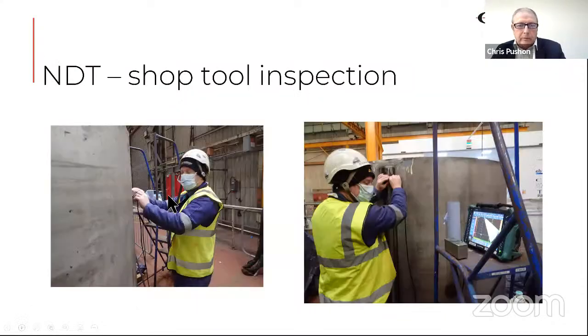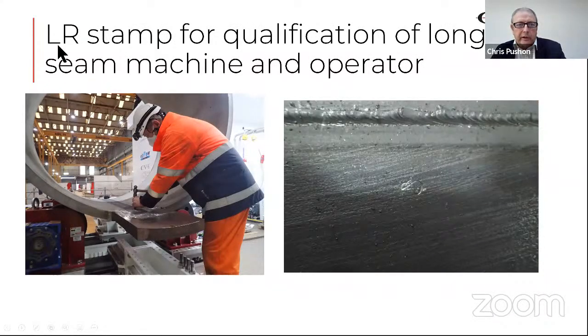Then we do a shop tool ultrasonic inspection. You can see looking at a phased array system. And then we invited a surveyor from Lloyd's Register to check that we carried out the welding procedure according to the parameters we put on our WPS. And he agreed we'd done it properly, and then he stamped it with his stamp.